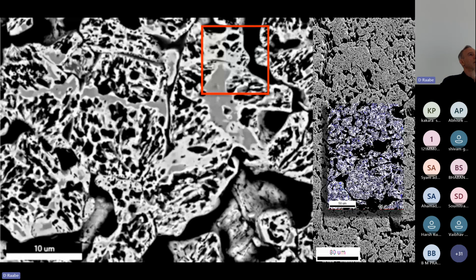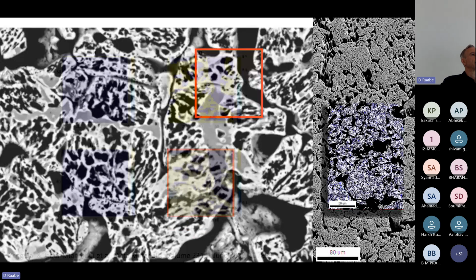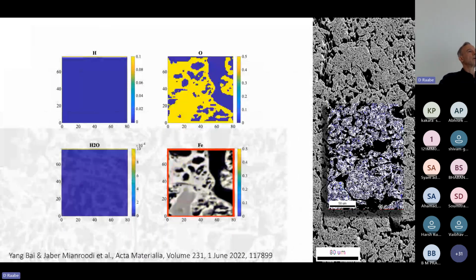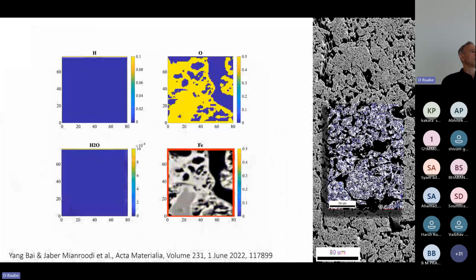And when you cut out such a patch as you see here, we also wanted to do a local boundary condition treatment in terms of theory. And this is now mesoscopic, a mean field theory, where we cast this phase transformation during the last step, where you transform the wüstite into the alpha iron, into a generalized form of the Ginzburg-Landau equation, which is nowadays also sometimes called phase field theory.